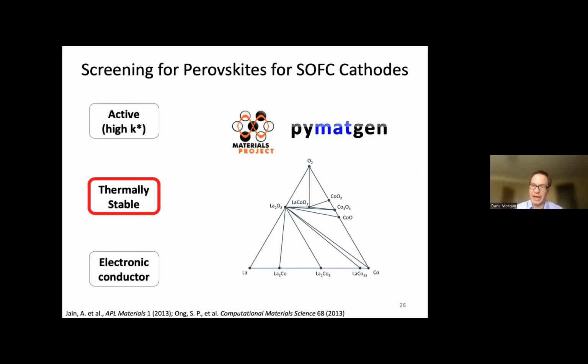Well, we're going to use a set of tools developed by the Materials Project, which is a very large database of hundreds of thousands of computed energies, against which we can compare any new perovskite and decide if it's stable. So they have a large database of energies and some very nice tools that let you basically calculate the phase diagram of any new material in light of all of those hundreds of thousands of calculated energies. So I can take any of our calculated perovskites and in just a few minutes decide, is it thermodynamically stable with respect to essentially all the known oxides in the world, or metals for that matter.